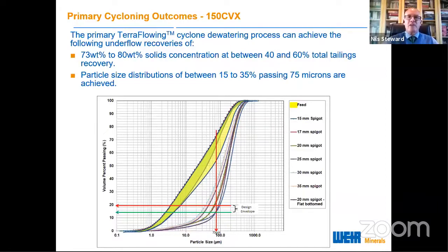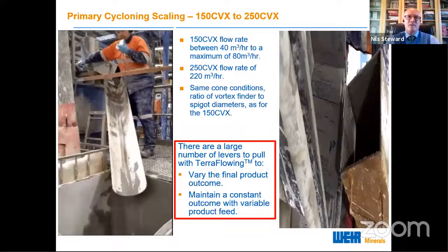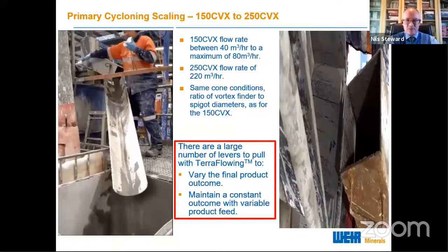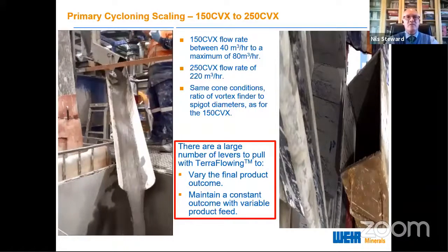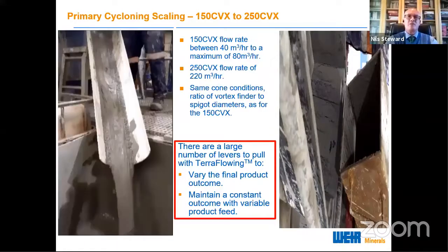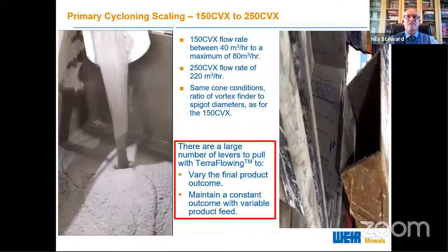And here you can see how we achieve different particle size distributions with the levers that we pull: flow rate, operating pressure, what we inject into the cyclone, which is part of our innovation, and then again, vortex and spigot sizes. Just to give you a flavor of what is possible from the underflow of our 150 cyclones, this is typical gold tailings, 100% below 300 microns. This is the primary underflow at around 80 weight percent solids.